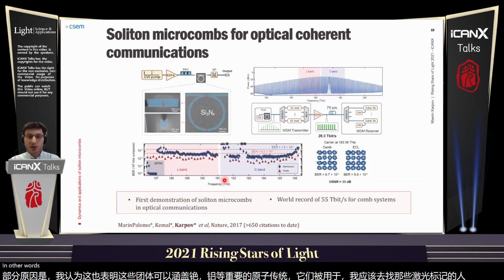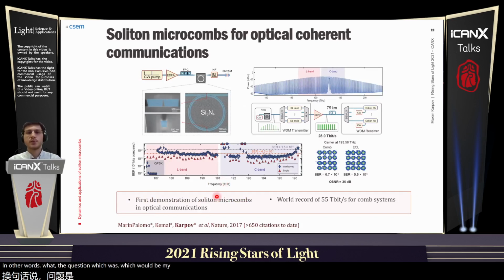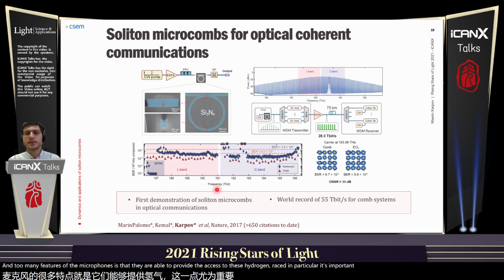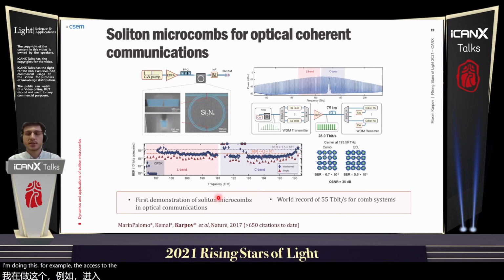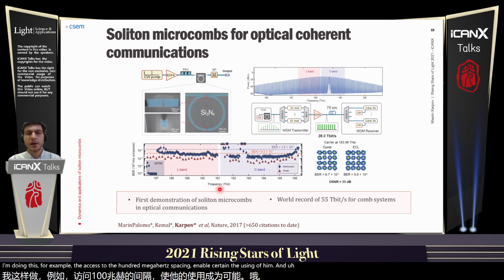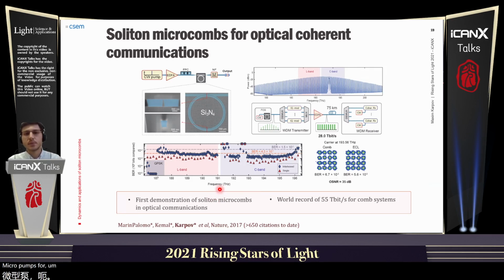Another very cool application which we demonstrated was for optical coherent communications. A main feature of the microcombs is that they provide access to high repetition rates. In particular, it's important because access to the 100 gigahertz spacing enables the use of microcombs for communications, because it matches the dense wavelength division multiplexing frequency grid of 100 gigahertz or 50 gigahertz.